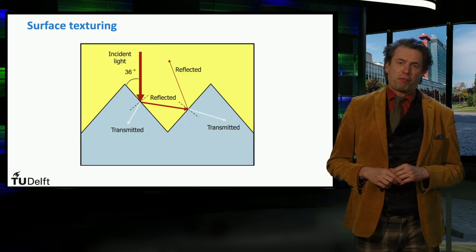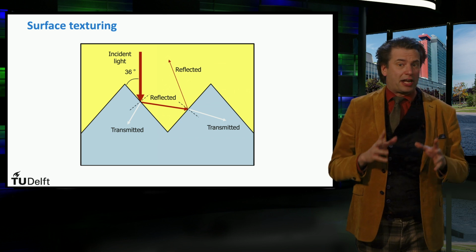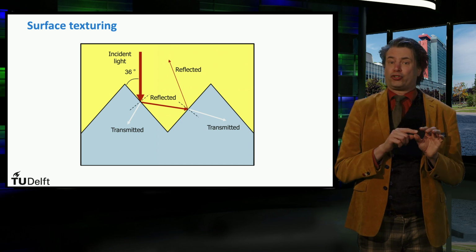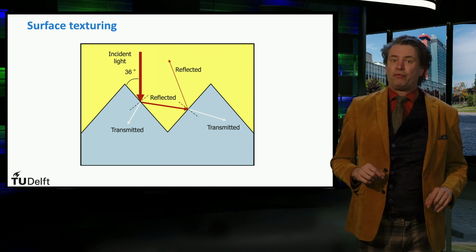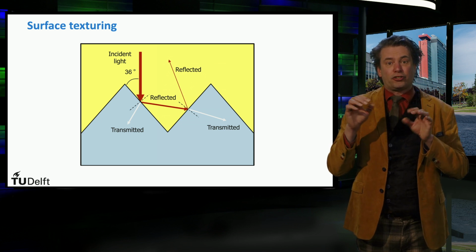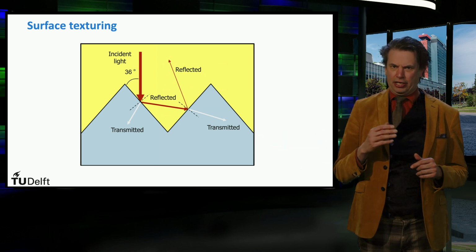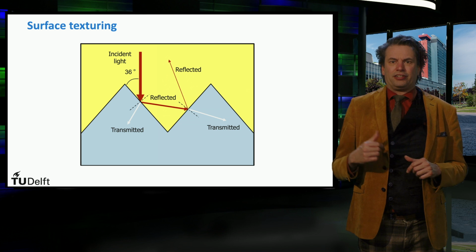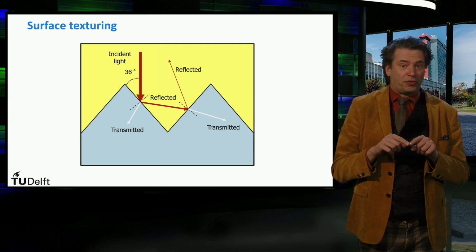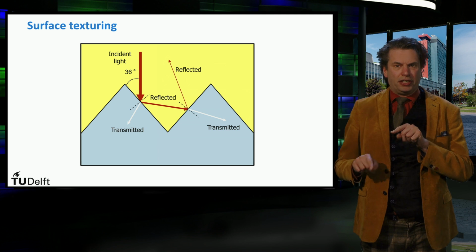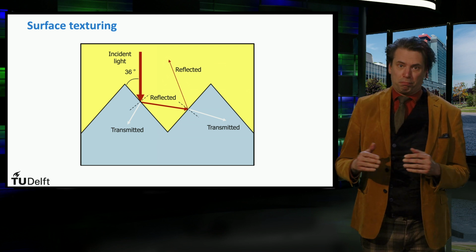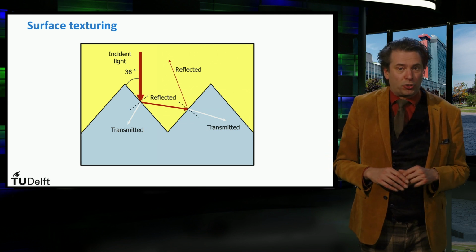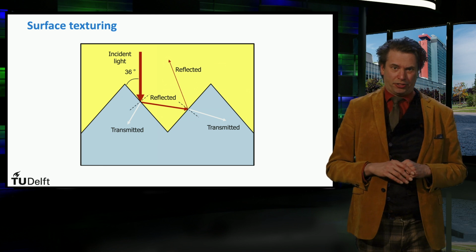As discussed in the first part of this MOOC, texturing of the surface can improve the light incoupling as well. Light that is reflected at the textured surface can be reflected at angles in which the trajectory of the light ray is incident somewhere else on the surface. Here, the light can still be coupled into silicon. Secondly, the scattering at the textured surfaces will couple the light under angles into the wafer. This means that the absorption path length will be enhanced. This certainly enhances the welcome absorption of the light with a wavelength above 900 nanometers.